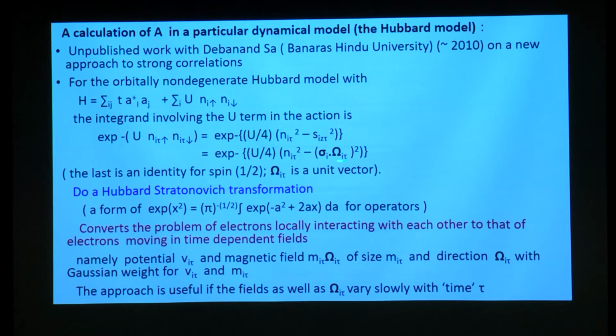Now you take this self-interaction term and do what is again well known, called the Hubbard-Stratonovich transformation, which is actually an operator generalization of the very simple result that exponential of x square can be written as this integral. The interesting feature of this is that here it is quadratic and here it is linear. So basically it converts the problem of electrons interacting with each other into a problem of electrons moving in some time-dependent potentials, which are the charge potential and the magnetic potential, with the Gaussian weights coming from this factor.